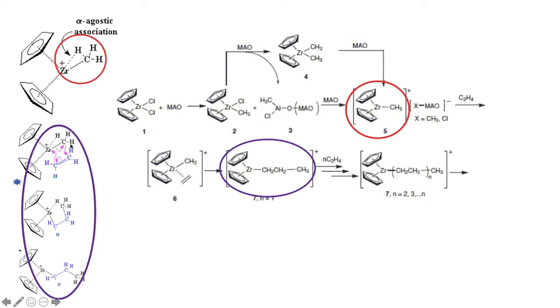Then the electrons in the zirconium-methyl carbon bond shift to form a bond between the methyl carbon and one of the ethylene carbons. Meanwhile, the electron pair that had been forming the alkene metal complex shifts to form an outright bond between the zirconium and one of the alkene carbons, leading the zirconium to end up just like it started, lacking a ligand, but with an agostic association with the C-H bond from the alkene monomer.